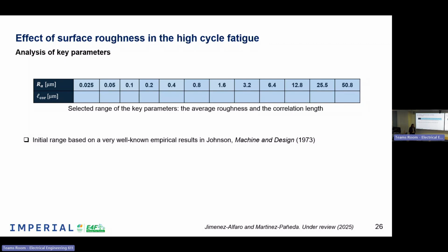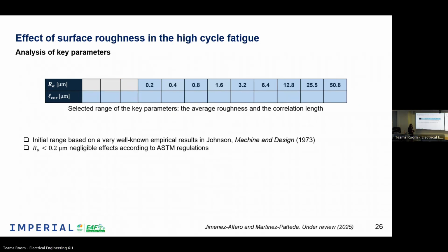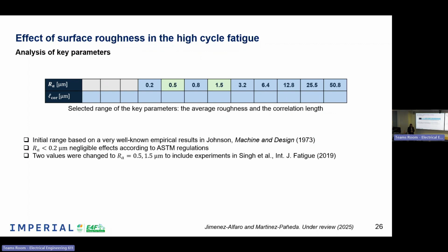Now, I would like to show you a comparison with key parameters. To define this, I have defined a range, and to define the range, we have based our values on the previous range defined by Johnson in the 70s. This is a very well-known experimental campaign, that's why I use it, but we have made some changes. First of all, if the roughness was less than 0.2, we have removed it, because according to the regulations, its effect in fatigue is almost negligible. Moreover, we have changed these 2 values just for the economy in the simulations, because we wanted to compare with experiments of Singh et al. So we just changed these 2 values.